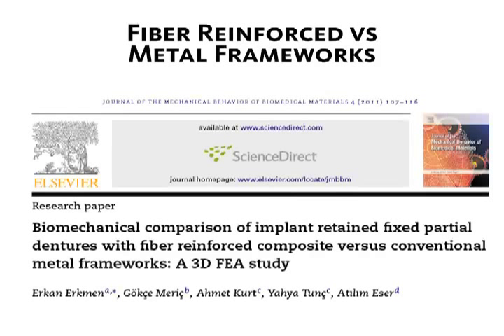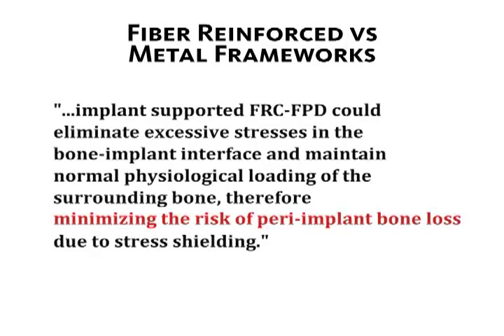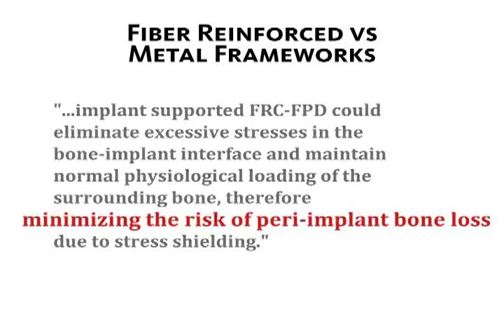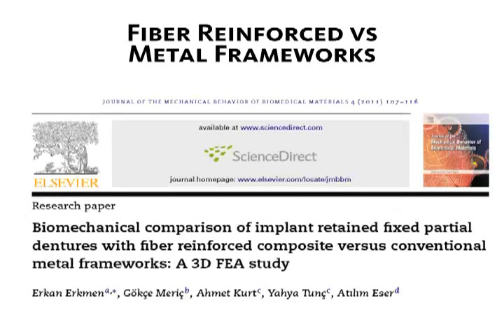Similar findings have been observed for fixed dental prostheses in a recent investigation where these authors have concluded that implant-supported fiber-reinforced composite fixed partial dentures could eliminate the stresses in the bone-implant interface and maintain normal physiological loading of the surrounding bone, therefore minimizing the risk of peri-implant bone loss. Well, these findings are relevant and they definitely need to be validated from a laboratory and clinical perspective. They have motivated us to further look at the mechanical behavior of composites when used for implant-supported reconstructions.